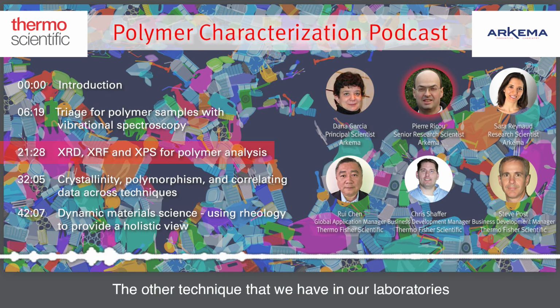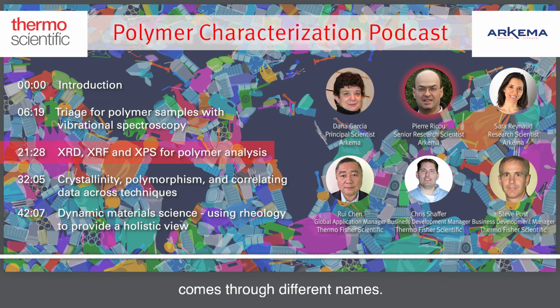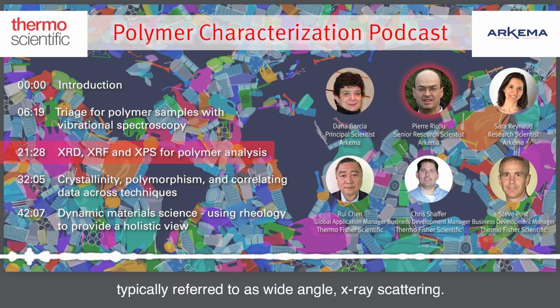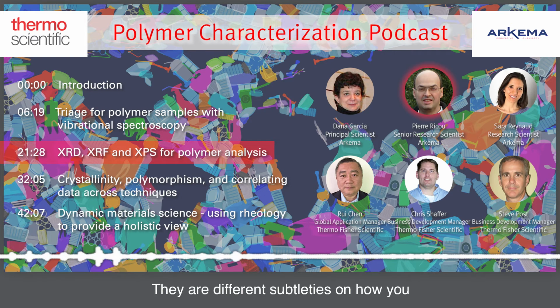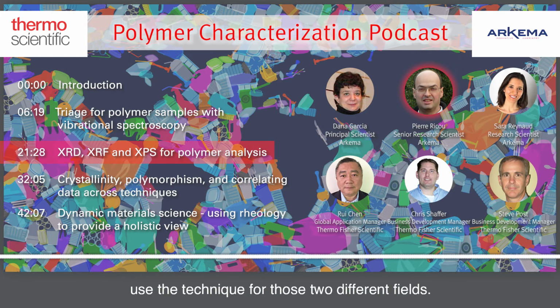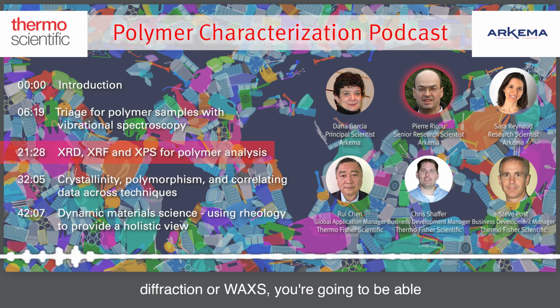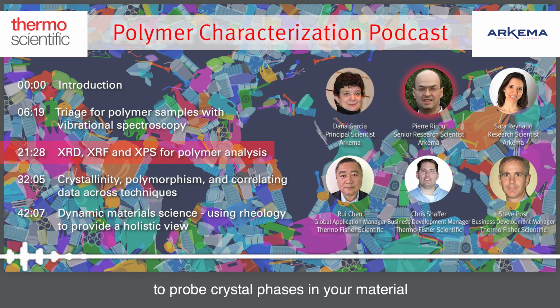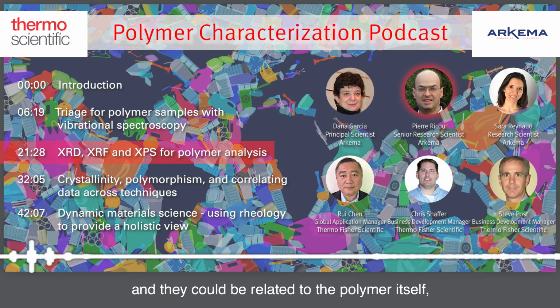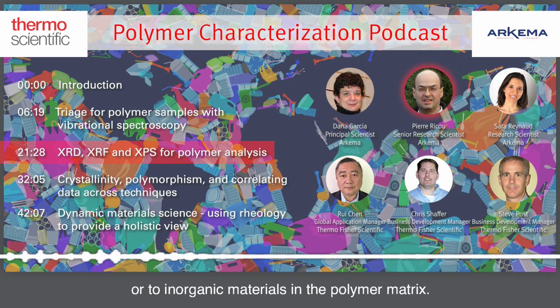The other technique that we have in our laboratories comes through different names. So it's X-ray diffraction, kind of known in that field for inorganic people. In the polymer field, soft material, typically referred to as wide-angle X-ray scattering. And there are different subtleties on how you use the technique for those two different fields. But basically, the idea is that with X-ray diffraction or WAXS, you're going to be able to probe crystal phases in your material. And that could be related to the polymer itself or to inorganic materials in the polymer matrix.